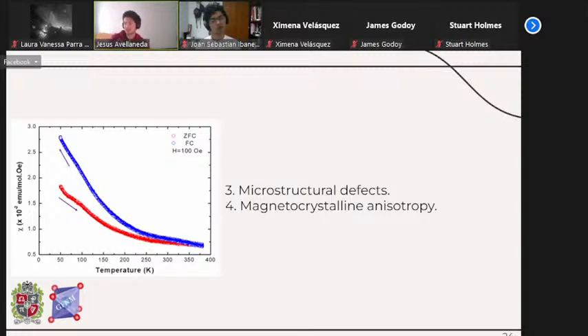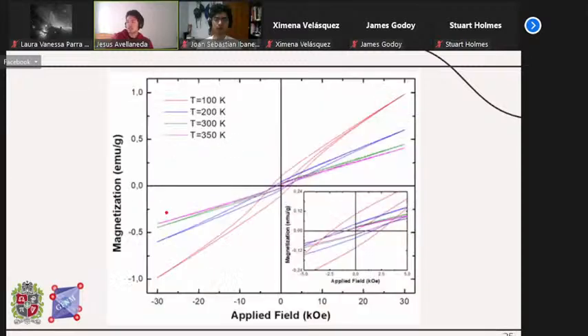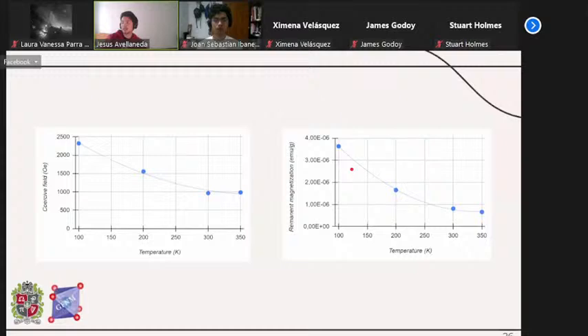Said intersection is of interest because it tells us the Curie temperature. As you know, the Curie temperature is the limit between the ferromagnetic and paramagnetic transition. However, we can safely state that the Curie temperature for this material is above 300 Kelvin at least. So with the hysteresis curves obtained, we proceed to analyze the ferromagnetic behavior, determining the average magnetization, the coercive field, and the remnant magnetization for each of the curves obtained right here. So those data are plotted in these two graphs.